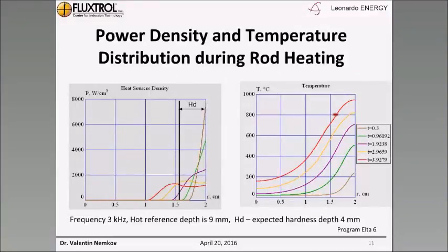Now, let's look a little bit at power density and temperature distribution during heating of a part of simple geometry, for example, a rod. Here we have the curves of the power distribution, watts per cubic centimeter, for different stages of heating. Here is the radius, and this curve corresponds to the beginning of the process when the part is completely magnetic, and you see that it drops very quickly. It's not exponential, but some kind of parabolic or even linear. When the temperature of the part grows, we have this green line due to change in resistivity and permeability, but the part is still magnetic.